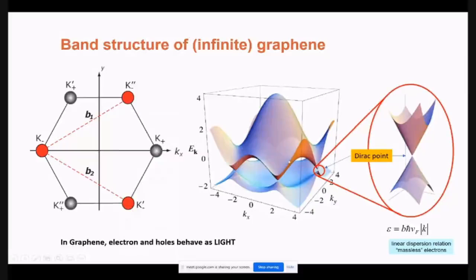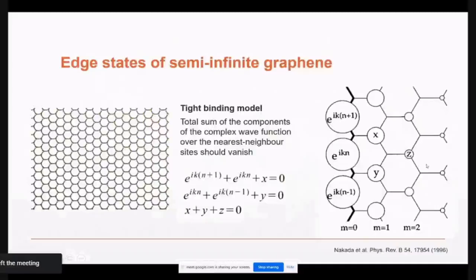I don't know whether you can see my cursor, but hopefully you can. If you see these points where the conduction band and valence band touch, they are what you call the Dirac points. Around the Dirac point, you have this conical band structure, which is why the dispersion relation at low energies is linear, and electrons in graphene behave as light, although at a much lower velocity, about 10 to the power of 6 meters per second. You get a linear dispersion. Okay, so that's the case of infinite graphene, and this is where the interesting thing starts.